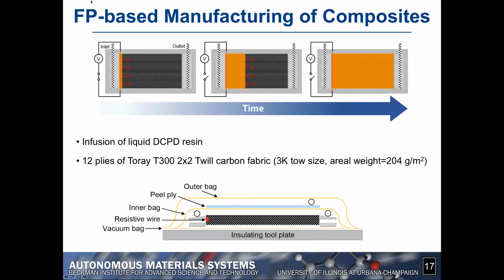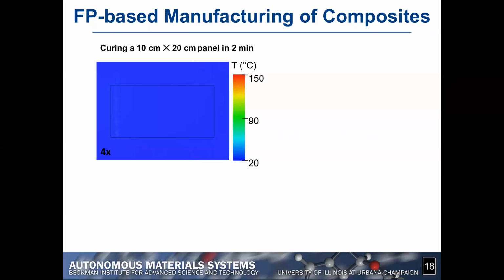And then, as schematically illustrated on the top, you introduce a little bit of heat using an embedded wire. We introduce a certain amount of heat, and then we basically turn it off once the front starts to propagate, and the front will actually propagate to the entire part, and you will end up with the fully polymerized, fully cured composite panel.